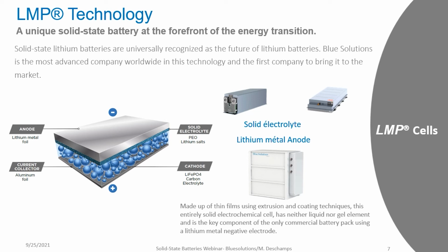LMP is the assembling of only 4 foils. On the negative side, a lithium metal foil. On the positive side, a composite electrode made of lithium iron phosphate, carbon, and electrolyte. This cathode is linked to an aluminum current collector. Between positive and negative side, the separator, a lithium salt dissolved in PEO-based polymer.